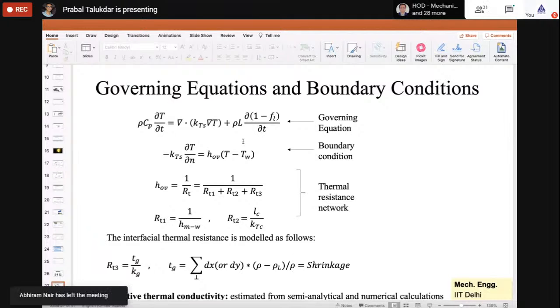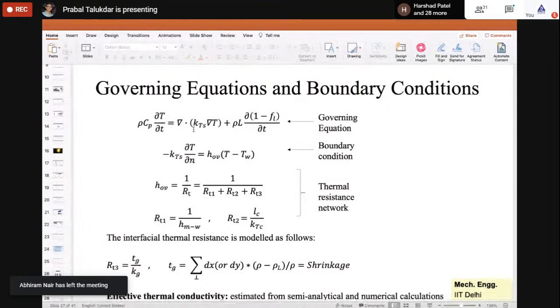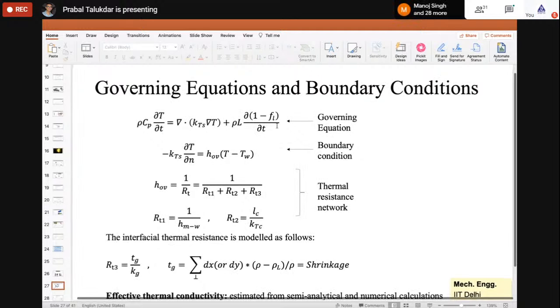So this is the governing equation. This is only two-dimensional heat conduction here. This is the transient term, and this is of course the latent heat term, the source term, which is required in the energy equation because of the latent heat transfer. So this term basically gives you the sensible part. This term gives you the latent part. And overall with this, he marches in the z direction with casting velocity.